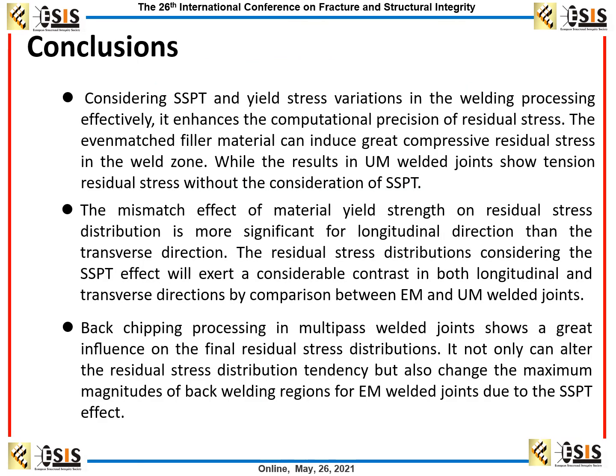we can summarize three conclusions. The first one is that considering SSPT and the yield stress variation in the welding processing effectively enhanced the computational accuracy of the residual stress. The even matched filler material can induce great compressive residual stress in the welded zone, while the result in the undermatched welded joint shows tension residual stress without the consideration of the SSPT effect.